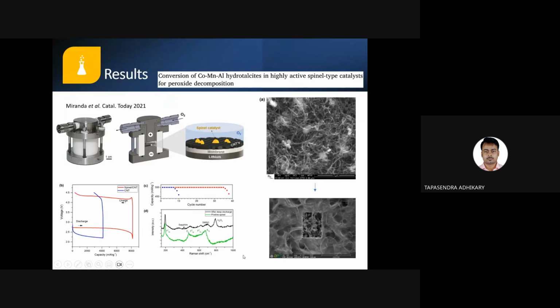You have shown in the Raman spectra the green one is for pristine and the black one is after cycling. As we can see, the DMSO electrolyte which you have used, after cycling the peaks are small, so does it mean that it decomposed while used in the batteries as an electrolyte? Since air and oxygen are there, does it have the possibility to decompose, and does the capacity fade happen due to that?